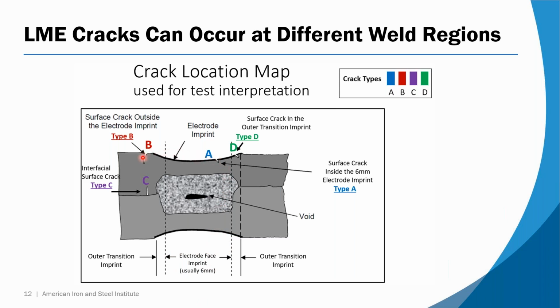Type B is decidedly not under the electrode. So it's off to one side or another, and it's away from the electrode imprint and also that outer transition imprint. When there's indentation of the electrode, more and more of the electrode begins to contact the metal. Okay, so it's a little different in this intermediate transition space than saying, okay, type B is where it never ever touched the electrode at any point during the weld process.